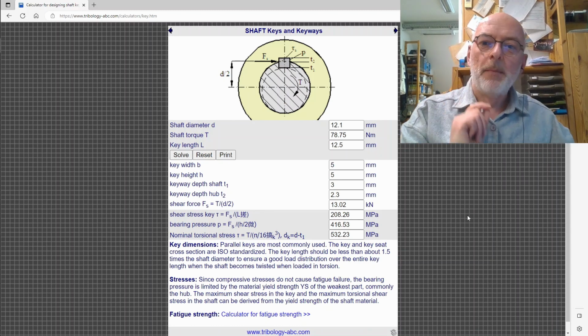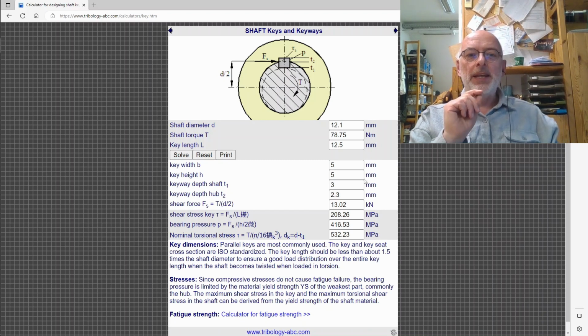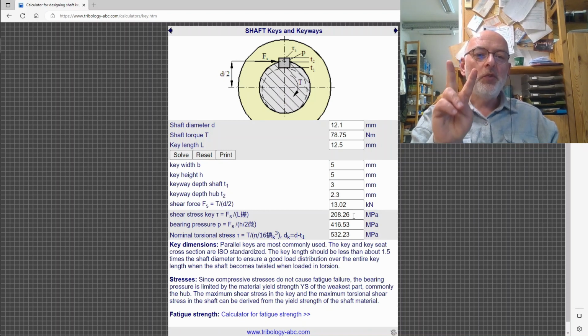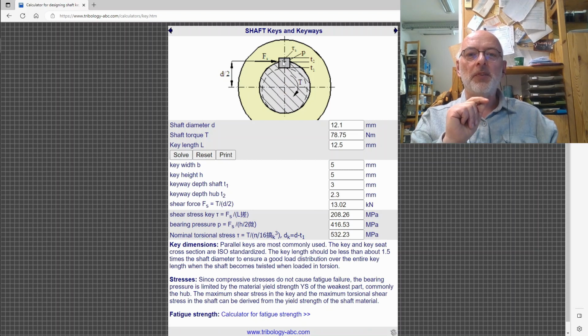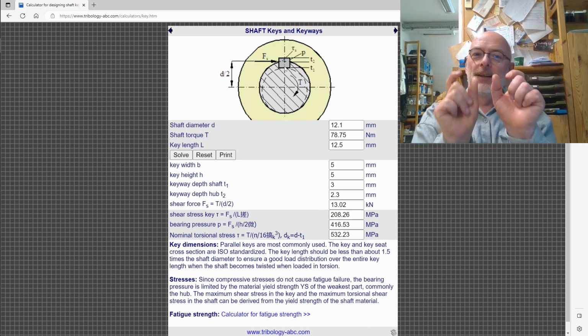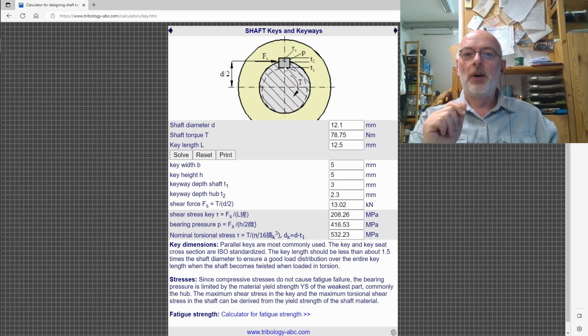Short update, I came up with a solution. So if we take a 5 by 5 millimeter key with a length of 12.5 millimeters, the shear stress is 208 megapascals. If we take 2 such keys, but not on opposite sides, but in series, so to say, so on the same side, but with a little distance, we're fine. Then that pressure halves effectively, and we are below the 105 megapascals my 6060 aluminum can take.